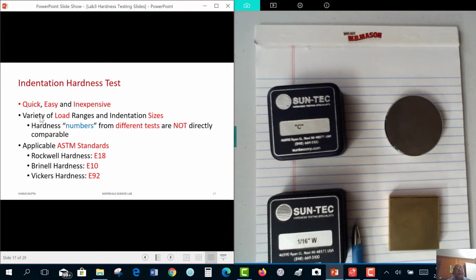Indentation hardness test is common because it is very quick, easy, and inexpensive. And there is a variety of load ranges and indentation sizes. We cannot really compare hardness numbers from different tests. So we cannot compare Rockwell C to Rockwell B or Brinell to Rockwell and so on and so forth. There are ASTM standards for each of these tests. For the Rockwell hardness test this week, become familiar with E18. In lab 1, hopefully you became familiar with E10. In a later lab, you will become familiar with Vickers hardness, called E92.